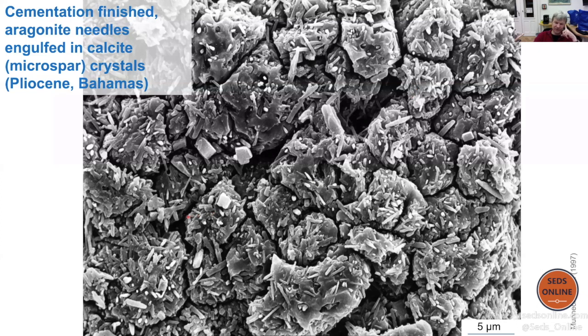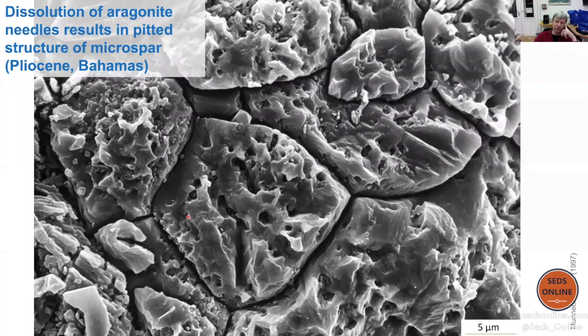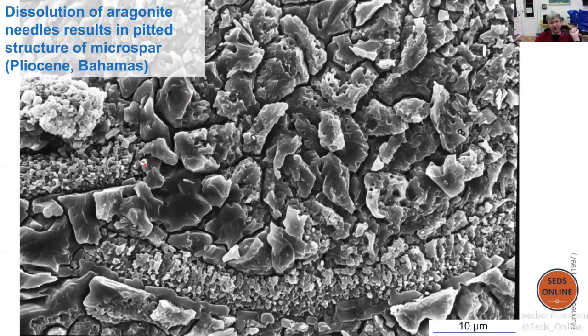So what would be the next step? It's the dissolution of the aragonite needles, and our microspar crystals will get these pitted structures, these empty pits, which are probably enlarged here a bit by the acid we have used, because these are etched samples. But we have microspar crystals with empty pits. This is still from the Clino core, so Pliocene in age. Another from the same core, we see two shells here. It's probably an ostracode shell, I'm not totally sure. But we see very sharp boundaries between the shell and the surrounding pitted microspar crystals, because they were basically growing until they reached each other and until they reached a shell. So this is Pliocene Bahamas.